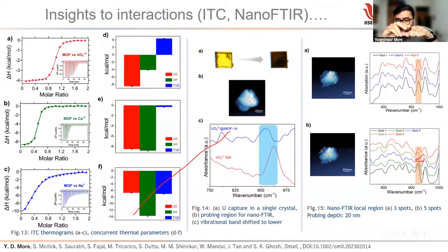And if some atom is going and sitting within the layer, whether it actually exists there, the best way is nano FTIR, because the cantilever of nano FTIR is a laser guided measurement in a nano confined area, where the cantilever will go only 10 nanometer down. It will touch within the molecule, then it will see whether that atom is here or whether that molecule is here or whether that bonding exists. So that was one of the brightest tools that we have.